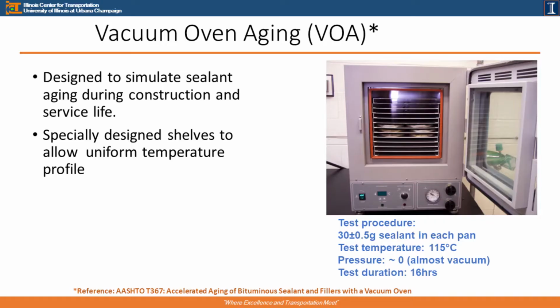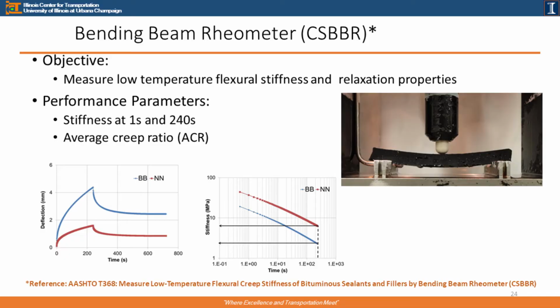They call it the vacuum oven aging system, designed to simulate sealant aging during construction and service life, with the cell specially designed to allow a uniform temperature profile. Then the bending beam rheometer, which is the same one, but they use a different term. Instead of the m-value, they use average creep ratio.